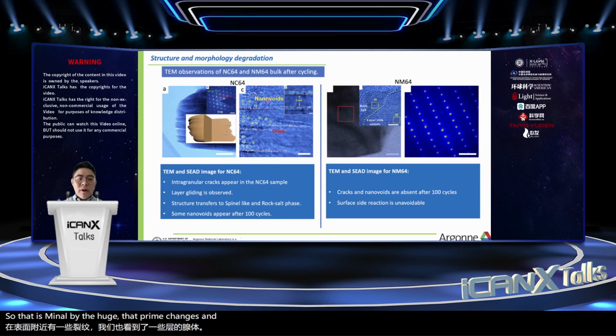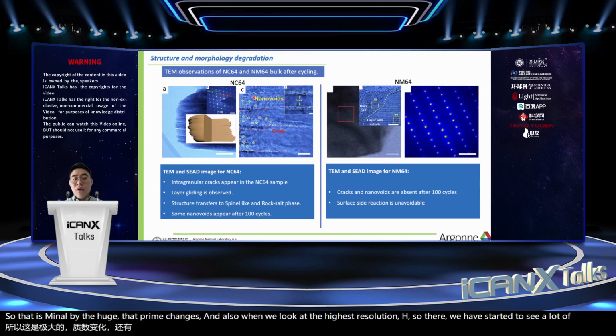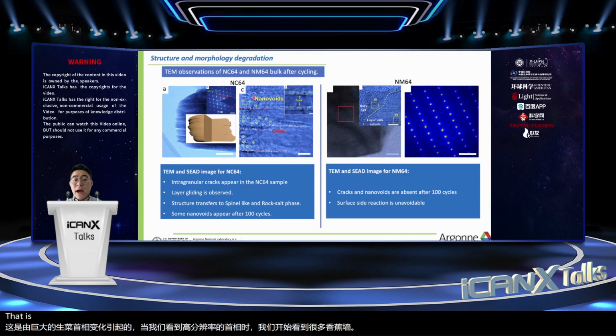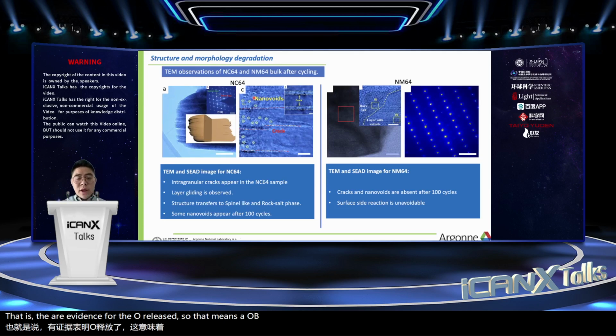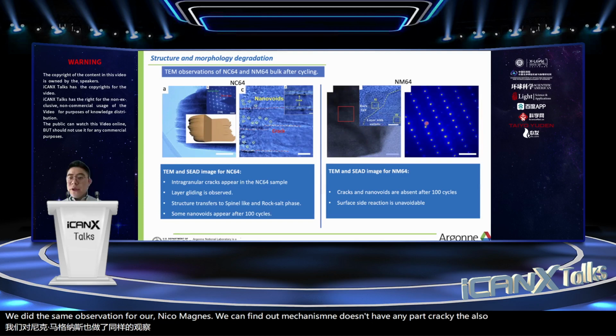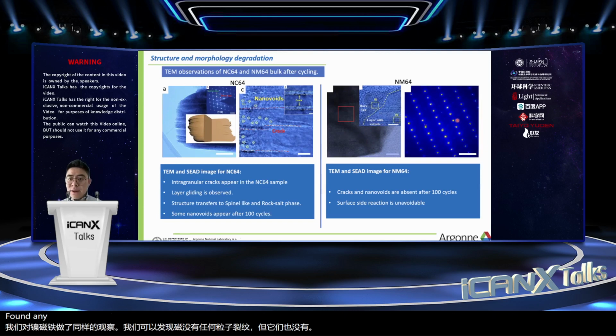And also when we look at the high resolution TEM, we have started to see a lot of nanovoids. That is the evidence for the oxygen release. So that means beside the structure changes, cobalt will also cause oxygen release from the lattice. We did the same observation for nickel manganese. We can find out manganese doesn't have any particle cracking, and we also do not find any structure evolution over the long cycles,